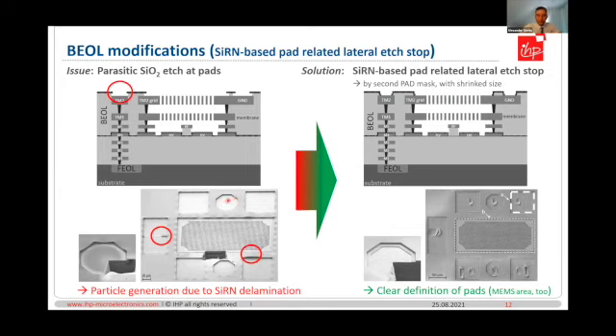To get rid of this problem, the solution is a silicon nitride-based pad-related lateral etch stop by a second pad mask, which shrinks the size. In this case, the leveled oxide on top of top metal 2 was first patterned by a standard pad mask. Then the silicon nitride deposition followed, and after that the second pad mask was used with a shrunk size. So we could realize this silicon nitride-based pad-related lateral etch stop. As a result, you see in these SEM images the pads are clearly defined, and we could use this even for the MEMS area. I'll try to highlight this here also. It's also working.